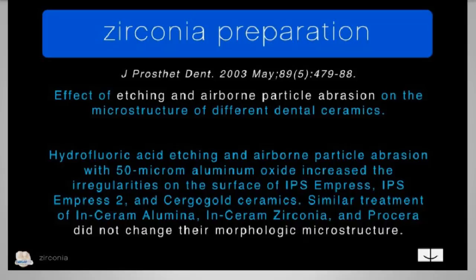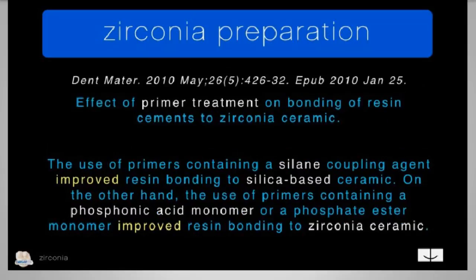Now, here's an interesting article that was published 12 years ago, because there's a lot of confusion. Can you etch it? Can you etch it with airborne particle abrasion? And it's interesting that this study showed that hydrofluoric acid etching and airborne particle abrasion did not change the morphologic microstructure of zirconia. Here's another one about priming it. So they wanted to use a resin cement with a zirconia. And they found that silane improved resin bonding to silica-based ceramic, not a surprise. But that a phosphonic acid monomer or a phosphate ester monomer was needed to improve the resin bonding to zirconia. So a different type of primer.